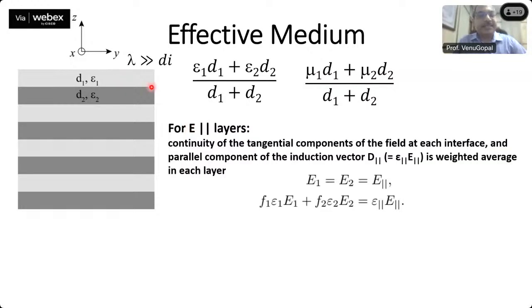In this case, we can distinguish, for incident electromagnetic radiation, whether the electric field is parallel to the layers or perpendicular to the layers. If E is parallel to the layers, whenever we do electromagnetic boundary value problems, we always look at continuity of the electric field and continuity of the first derivative of the field. So we get that the tangential component of the field at each interface is continuous, and also the induction vector D parallel, which is equal to epsilon parallel E parallel, will become a weighted average over each of these layers. That means E1 equals E2 equals E parallel, and F1 epsilon 1 E1 plus F2 epsilon 2 E2 is equal to epsilon parallel E parallel.